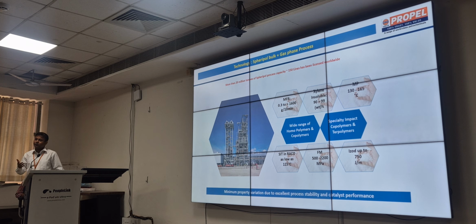And when we are going to produce a no-break grade, which is greater than 500 joules per meter Izod impact strength, getting the distribution is much more of a challenge. So the rule is that anything has to be compatible, it has to be of a similar nature. Because in the first reactor, in ICP grade production, you are producing polypropylene. In the second reactor, you are making EPR. This EPR has to be distributed in the polypropylene matrix.